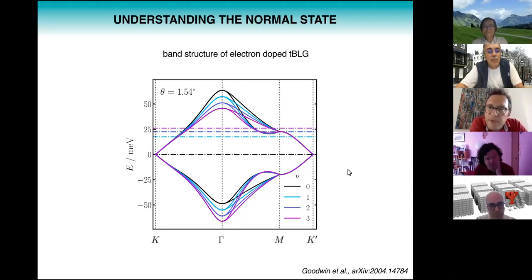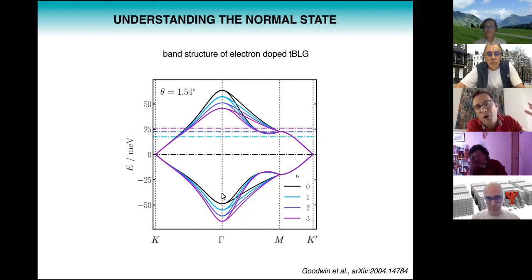Now there's a couple of interesting observations that you can make from this band structure. In particular, doping leads to a distortion of the band structure. The band structure becomes less electron-hole symmetric than it is in the neutral system. The more electrons you add, the flatter the conduction band becomes, but on the other hand, the valence band becomes more dispersive. So the overall bandwidth doesn't change by that much, but the bandwidth of the conduction band becomes smaller, and the bandwidth of the valence band becomes bigger as you dope electrons.